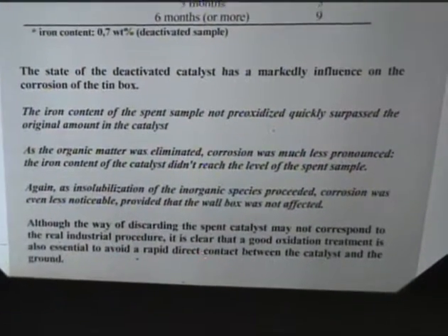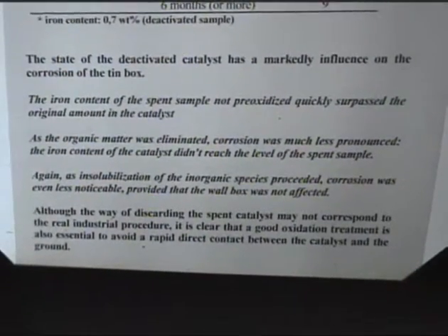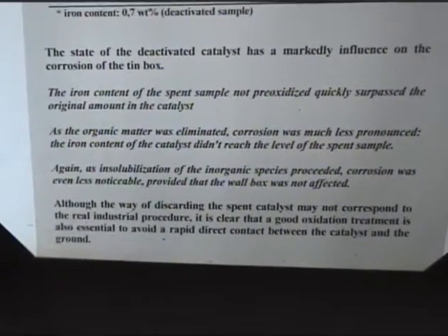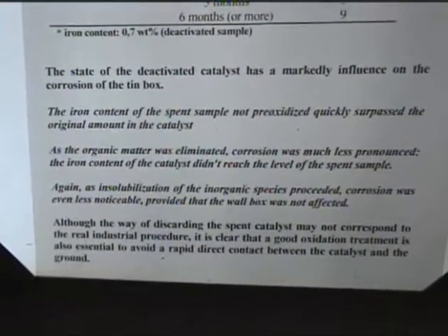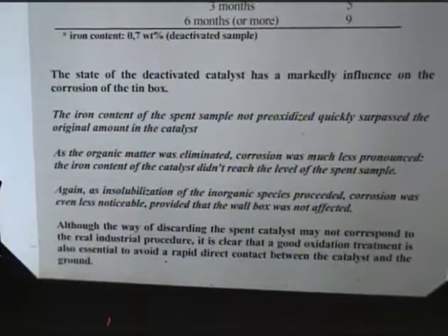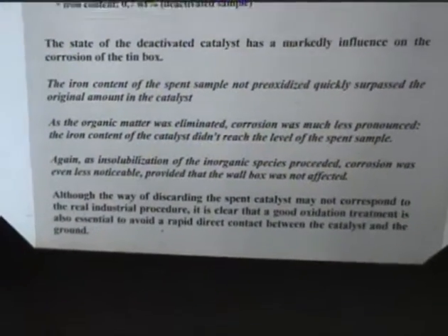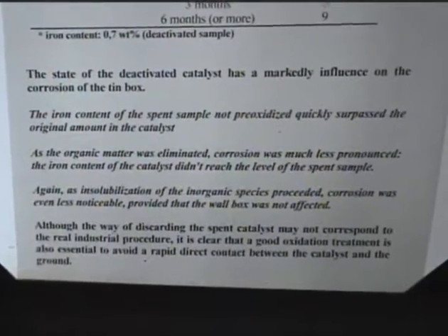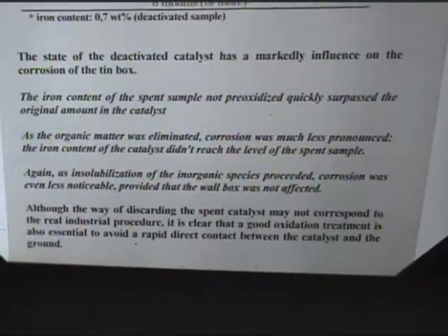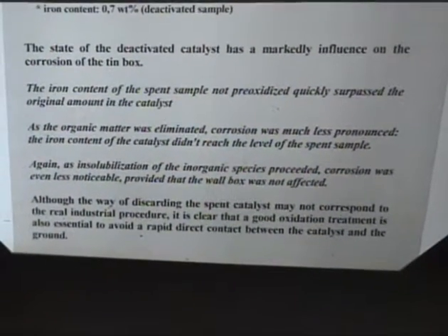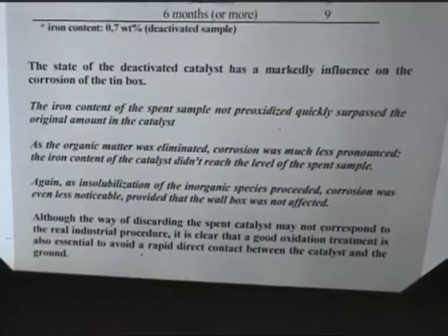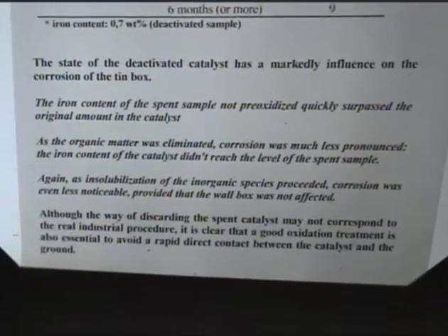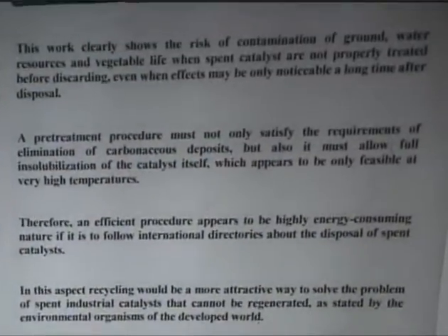Although the way of discarding spent catalysts, as shown in this work, may not correspond exactly to the industrial procedure, it's very clear that a good oxidation treatment is essential to avoid a rapid direct contact between the catalyst and the ground due to the corrosion of the boxes. Some conclusions, but this is not the last transparency.